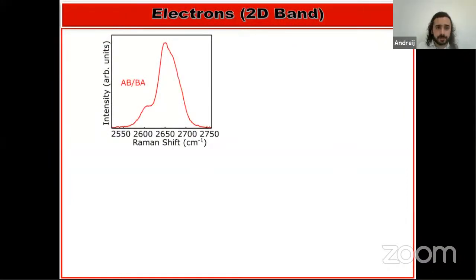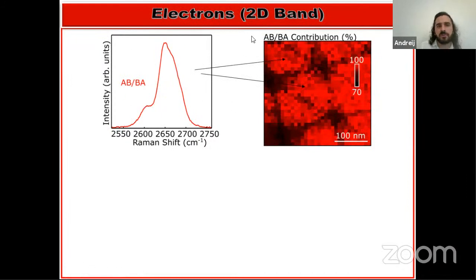Okay, we can also investigate electrons through the 2D band. The shape of the 2D band is related to the electronic structure and other features as well. And here I show the local spectrum at the ABBA site from the rTBG. Those of you that are experts on the Raman spectroscopy of graphene may say that this is very similar to the Bernal bilayer. Well, that's true. And when we plot the contribution from this spectrum over the space, we observe larger intensities at the ABBA sites, which are like Bernal bilayers.